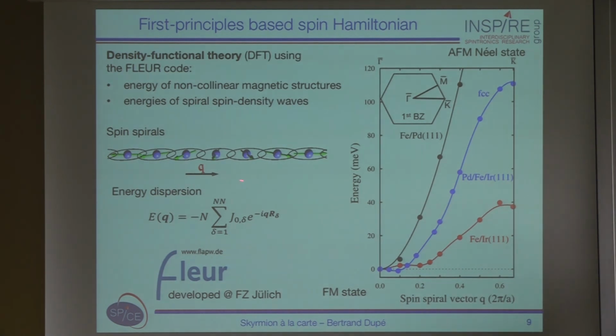So then when you have this information of the energy as a function of the spin spiral vector q, you can project this energy onto, or parameterize, an extended Heisenberg Hamiltonian where you have exchange interaction which is beyond first nearest neighbor. So this is an example that I'm showing here. This is the energy as a function of the spin spiral q vector for 3 different systems: iron on palladium 111, palladium iron iridium 111, and iron on iridium 111.